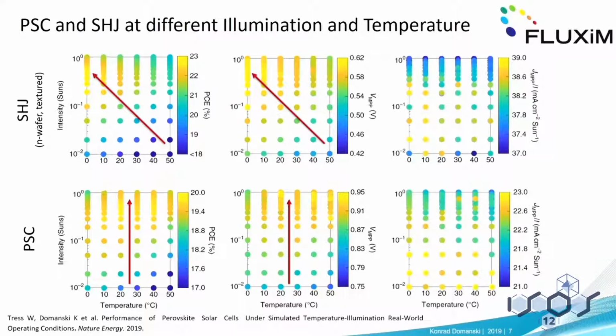it behaves a little bit differently. Here we already normalized the current for the irradiance that the cells see. And we see only a slight decrease going towards lower illumination, but actually this is pretty small, and they behave linearly together, which is nice for tandem devices if you think about it. Because once you match the current in the tandem, they remain matched regardless of the temperature of the device, and they also behave linearly with irradiance. So that's good news for tandems of those devices.